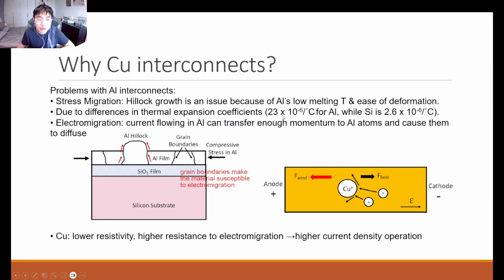However, there were certain problems with this system of aluminum interconnects that actually drove the change to a copper-based system. One of the problems was this idea of stress migration. When aluminum was used as an interconnect metal, we observe things like hillock growth that you can see on this diagram on the left. This is because of the low melting temperature of aluminum and therefore its relative ease of deformation. So aluminum is a relatively low melting point metal and therefore can be easily deformed, especially when processes are being performed on it at elevated temperatures.